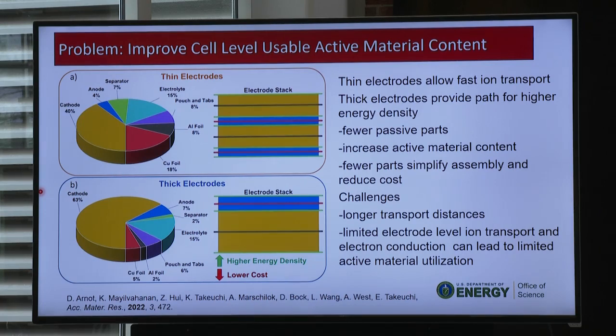But if you change how you design the cell and change how you package it, if you make a thick electrode, the amount of inert material, such as separator and current collectors, decreases substantially, and you can increase the energy content of the battery. But the downside is, now the ions have further to go. It's fundamentally a transport problem. We have to be able to get the ions to every particle. We have to be able to get the electrons to every particle.